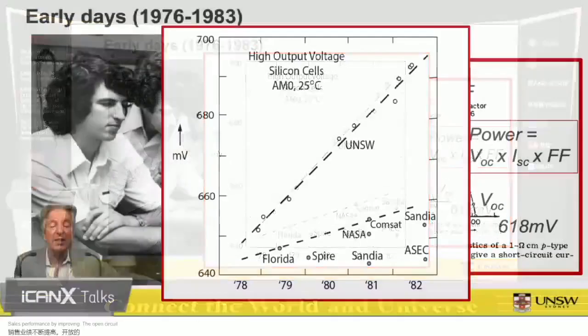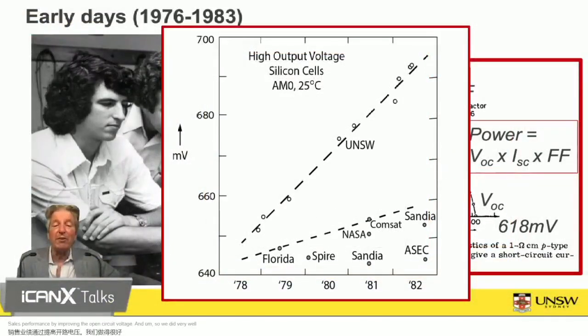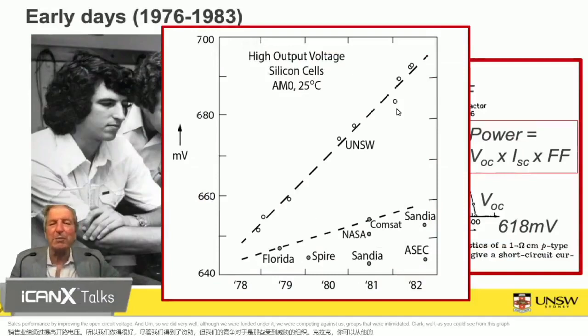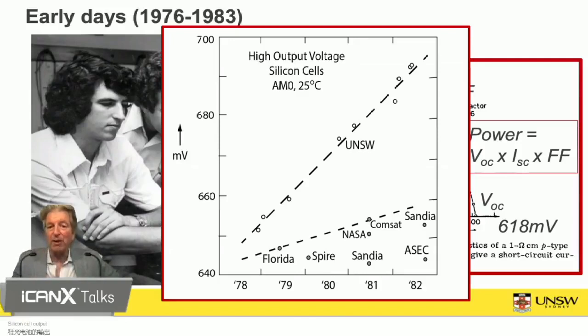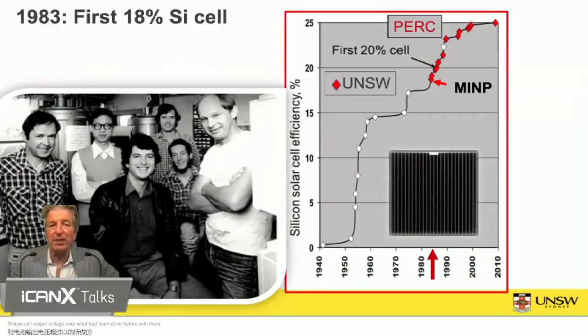So we did very well in terms of increasing that open circuit voltage. We didn't need very sophisticated equipment to measure this or to produce the devices producing it. But NASA had initiated a program to improve cell performance by improving the open circuit voltage. And although we weren't funded under it, we were competing against US groups that were, and did quite well, as you can see from this graph. We managed to substantially improve silicon cell output voltage over what had been done before with some unique structures.